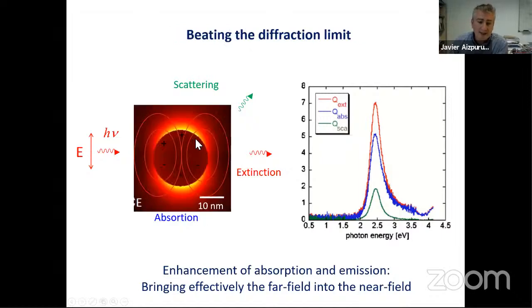Okay. The interesting thing again happens right in the effective mode volume. So now around the nanoparticle, the electromagnetic energy associated to the plasmon is trapped. Here I show you this basic resonance, the dipole resonance. This is positive, this is negative. This would be oscillating at optical frequencies. And the interesting thing, as I say, is that this effective mode volume, even if it's open, is very reduced compared to the wavelength. Imagine that we have 600 nanometers optical light wavelength, and this particle is of the order of 10, 20 nanometers. So we are reducing by factors of 50 or 60 or 100 the wavelength into the dimensions where we trap that photon, right? Those photons associated to the incoming light.